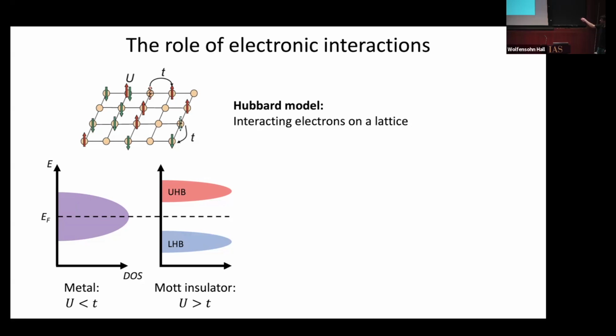Basically, this on-site interaction, it's disfavored to doubly occupy a site because it costs such a large energy penalty. And in that case, you get the band splitting into a lower Hubbard band and an upper Hubbard band, and you have charges basically pinned one charge per site. In this model, that's known as a Mott insulator. So this is the case for short-range interactions.